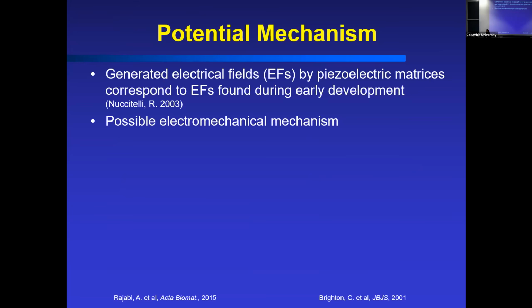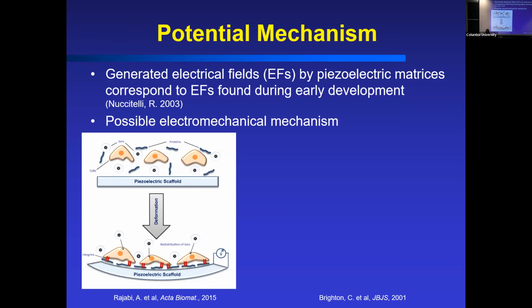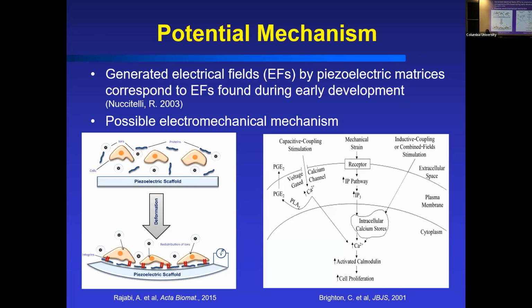And we can also look at potential mechanisms for, again, designs that we may be thinking about that may be important as a next stage for cartilage regeneration. So the potential mechanisms, again, these electric fields that are generated are pretty similar in levels to what you see during early development. And because you're forming these surface charges, you're probably getting changes in the surface of these materials. So we're looking at that more carefully. Adhesion of proteins, changes in local ion distribution can be affected. And then that's going to change how the cells are going to be sensing that environment. So you may be getting calcium influx. Others are showing some of that. Again, with electrical stimulation, you're getting this calcium influx, and that can alter that whole mechanotransduction signaling.